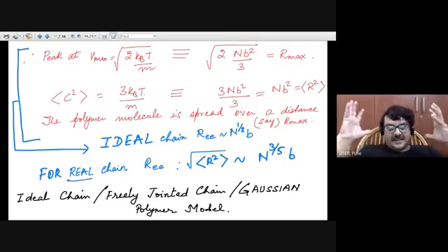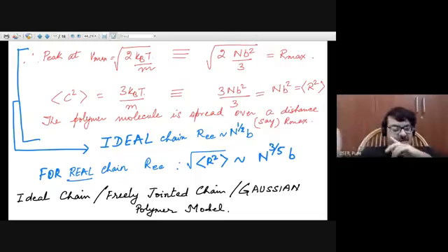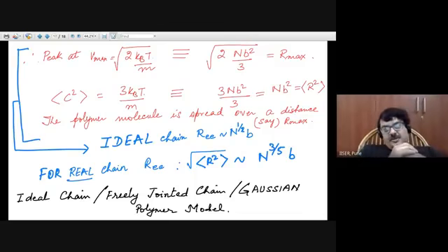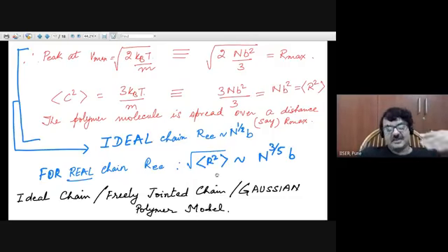If you take an approximate estimate of the volume this chain occupies in a dilute solution, not interacting with other polymer chains, then this real chain, because its approximate spread is 4 times that of an ideal chain, spans a volume that is actually 64 times that of an ideal chain. So we shall need to discuss real chains as well, but we have to wait for a few classes.